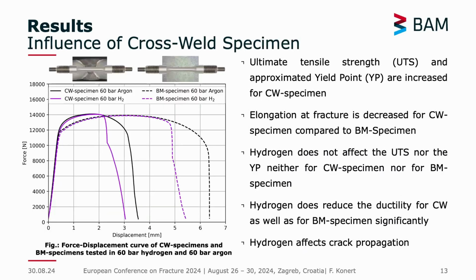And with this, I also want to come now to the cross-weld specimen. So as you can see on the upper left, there's the specimen geometry in solid lines, just across the whole weld metal, the heat affected zone, as well as the base metal, and as a reference only the base metal in the dashed lines. And yeah, if you just compare them for the reference specimen in the black colored lines, you just see that you